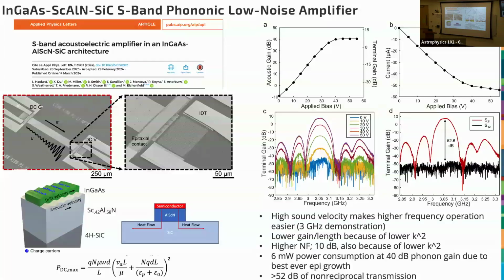We still have the indium gallium arsenide semiconductor, but we've replaced the piezoelectric acoustic material with aluminum scandium nitride, which is another piezoelectric material. It's not quite as good as lithium niobate, but it can be nicely sputter deposited on top of silicon carbide. Aluminum nitride with no scandium in it is perfectly lattice matched to silicon carbide. Aluminum scandium nitride is a little bit mismatched, but you can slowly increase the scandium concentration as you grow it, and you'll get relaxation that will not cause dislocation.